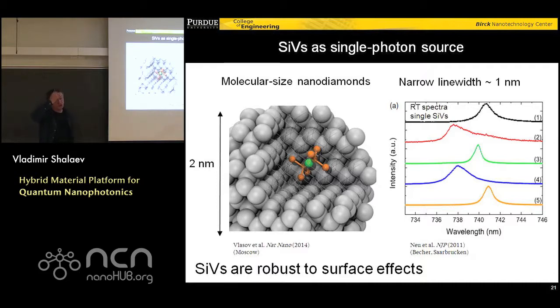So what you could do if you employ this type of vacancy with a very narrow line, and if you have very strong enhancement in the efficiency of generating photons, so that the photons are generated within a time shorter than the inverse of the width, meaning shorter than the decoherence time, then you would get indistinguishable photons at room temperature. For that, you need very efficient enhancement of the rate of generation. And that's exactly what our group and some other groups are working to accomplish.